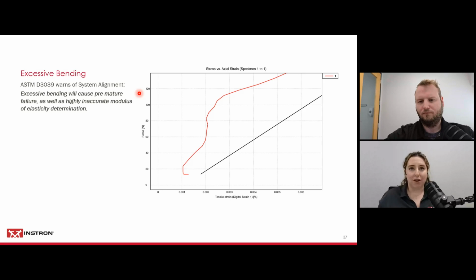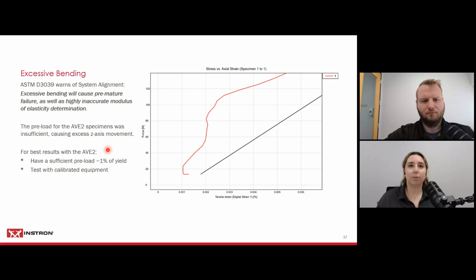So the AVE2 is not only very accurate in the X and Y, in the axial and transverse directions, but also in the direction coming in and out of the lens of the camera. So Stefan, if you could hit a couple times, thank you. Again, preload for my AVE2 specimens was insufficient, and we can see this in my graph on the right, where I've zoomed in at 1,000 and 3,000 microstrain. So what we want to do here is have a sufficient preload of around 1% of yield. My preload should have been at like 260 newtons and 660 newtons,